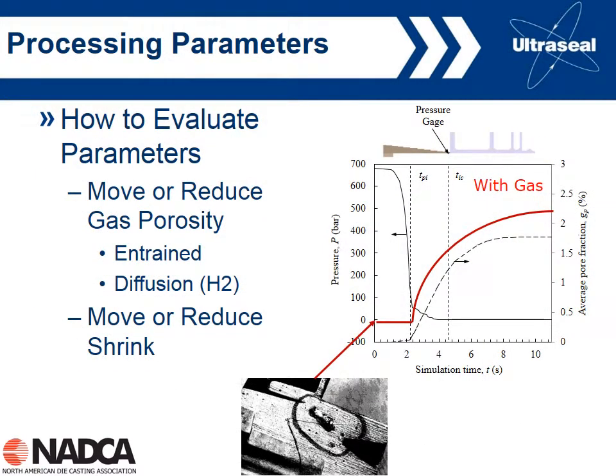So how do we start to evaluate these process parameters? Again, we should really think of porosity as a superimposed problem, coming both from shrinkage as well as from gas entrapment. Typically in die casting, shrinkage is going to dominate the location of the porosity, and then gas entrapment is going to either increase or decrease the amount of that porosity. And then the entrapped gas often becomes associated with shrinkage. And again, this is another one of the reasons why we can often see shrinkage pores that seem to have a spherical shape as opposed to the jagged shape we would expect.